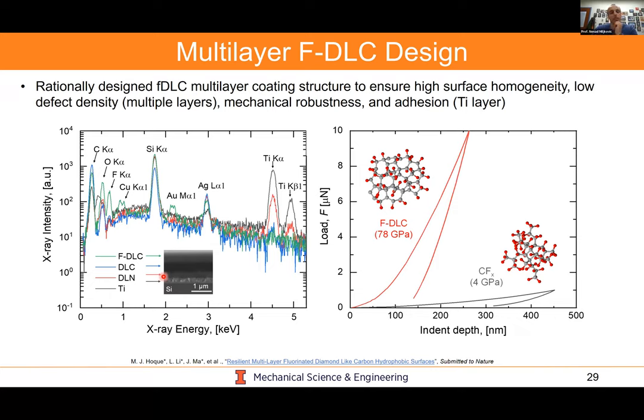So we're not talking about polymer coatings here. DLC being conventional diamond-like carbon and providing us with a buffer in terms of material properties to have a gradient in the material properties. And then at the end, this 500 to 600 nanometer layer where we co-deposit a fluorine chemistry with diamond-like carbon to really give us a volumetric hydrophobicity. If you were to look at the load profile as a function of indent depth during nanoindentation, you could see that FDLC has metallic-like properties, whereas this CFx formulation, which we typically use and a lot of groups use, we're talking about 4 gigapascals. Here we're talking about on the order of 80 gigapascals. So it's a very strong material.